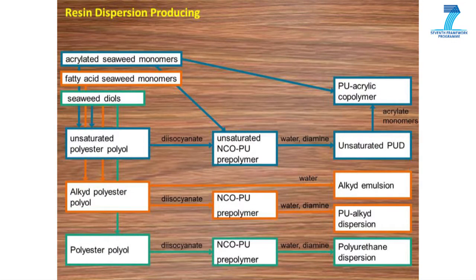Developed monomers have been successfully integrated into different prepolymers that resulted in stable water dispersions. There were proposed three different synthesis routes for various types of application. All of them are one-component system and most of them get their final properties by physical drying. In contrast to two-component resins, no pot lifetime has to be considered and less waste is expected. The three synthesis routes base on different types of chemistry of the coating resin: polyurethane dispersion, alkyd and alkyd hybrids, as well as polyurethane acrylic hybrids. All resins were based on seaweed monomers.